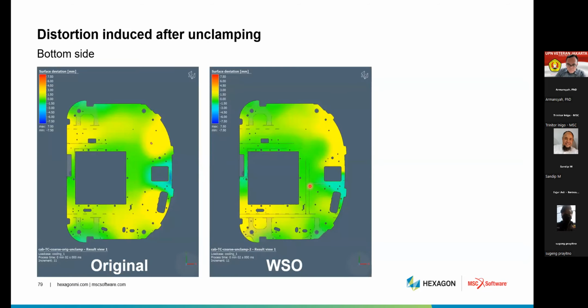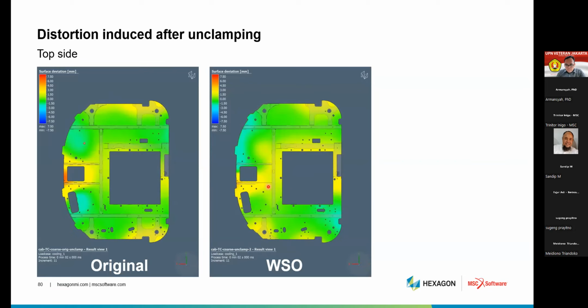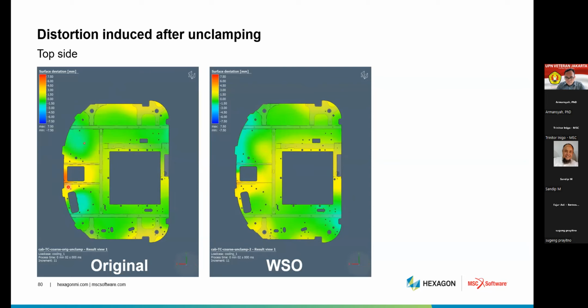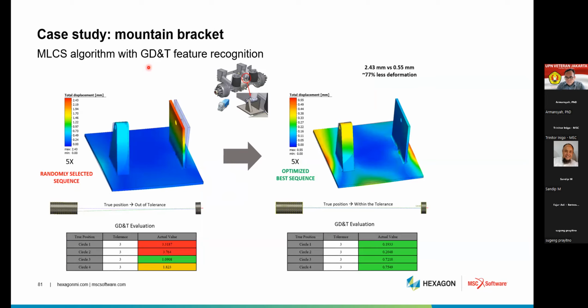Again, this is from the bottom side. After unclamping, you can see there is less distortion over here. Another case study is on the mounting bracket. This was very important because the components should be within tolerance to get the fitment. Earlier, with the original weld sequence, there were a lot of red areas, which means these are out of the tolerance values. When we predicted the weld sequence and did the welding, we can see everything is in the green zone, so it is within the tolerance levels.